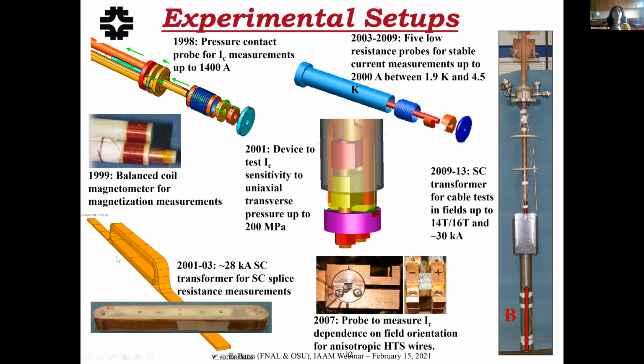So you can look at this one on the bottom left, which has a primary coil inside, which induces close to 30 kiloamps on your secondary. So that's how we resorted to testing our Nb3Sn cables, which go very easily to this level of currents by just powering a superconducting niobium titanium primary with a few hundred amps. So this is all the work that was done